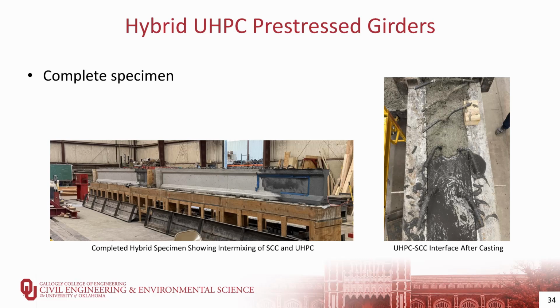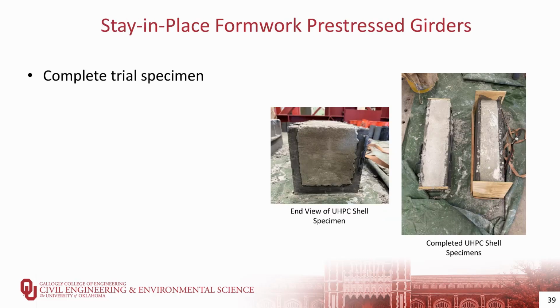So I could take a start, Omar. On the UHPC shell trial specimens that we did, one specimen was just completely smooth on the inside. There was no mechanical anchorage. There was no inside texture other than you sandblasted those, right, Omar?